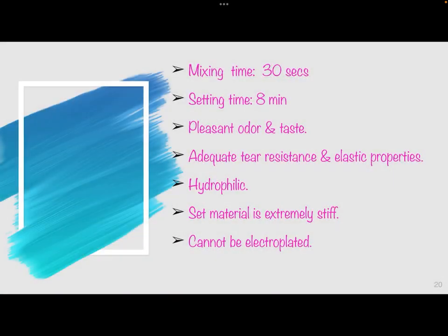Coming to the properties, it has a mixing time of about 30 seconds and a setting time of about 8 minutes. It has a pleasant odor and taste. It has adequate tear resistance and elastic properties. It is hydrophilic in nature. Once it is a set material, it is extremely stiff and it cannot be electroplated.